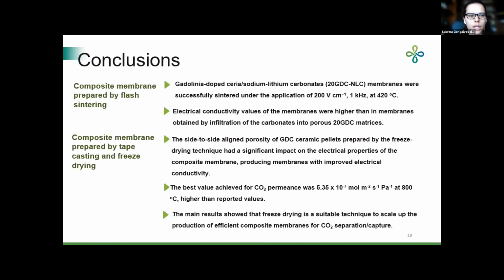And to summarize, the membranes were successfully obtained by flash sintering at a temperature of 420 degrees C, and those samples have higher electrical conductivity than the membranes obtained by infiltration. And in the study of freeze drying membranes, the side-to-side aligned porosity of the samples prepared by freeze drying had a significant impact on the electrical properties of these composite membranes. We could improve the conductivity. We achieved a high permeance value for this membrane, and these results show that freeze drying is a suitable technique to scale up the production of efficient composite membranes for CO2 separation and capture.